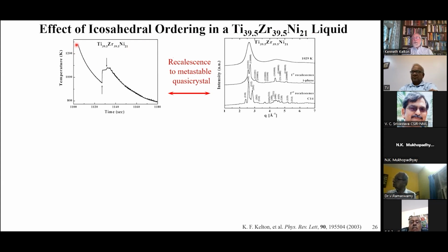Here's that liquid processed in the ESL that I showed you. We've heated the sample well above the melting temperature. We turn off the laser and it starts to cool, well into the supercooled state. It then has a sudden release of heat, a sudden increase in temperature as it begins to nucleate and grow, releasing the heat of fusion. This is called a recalescence. So it had a first recalescence, and then there was a plateau, followed by a second recalescence. Whenever you see this, it's a good illustration of metastable phase formation. So what we were doing was forming a metastable phase first, followed by the formation of the stable phase.